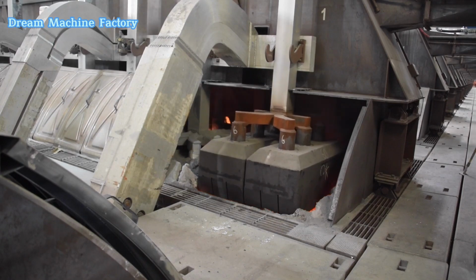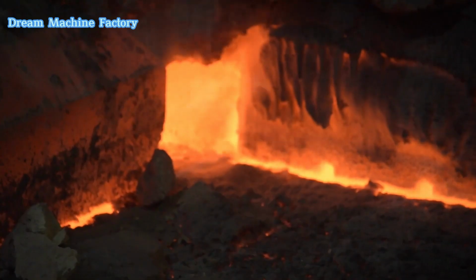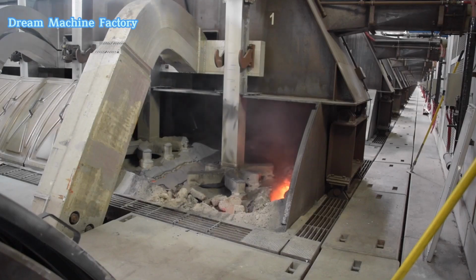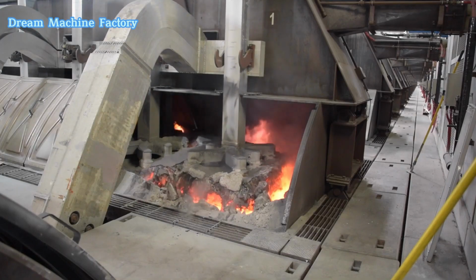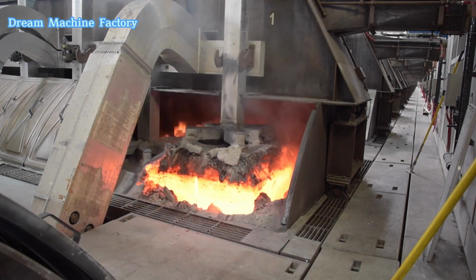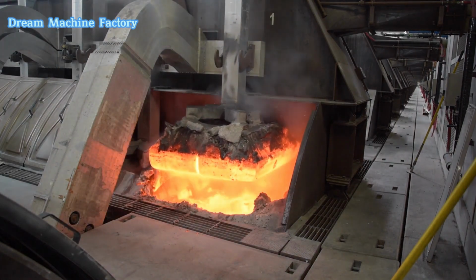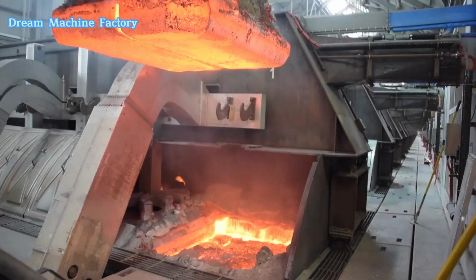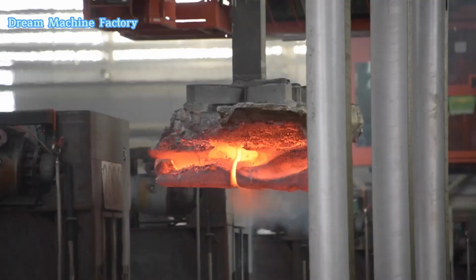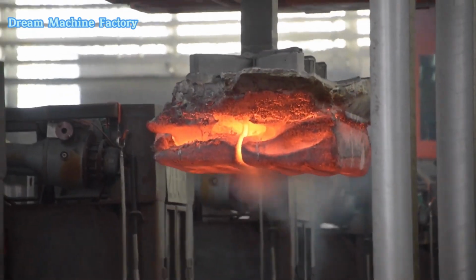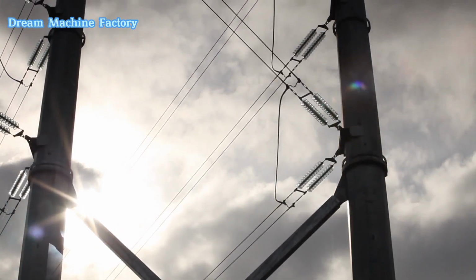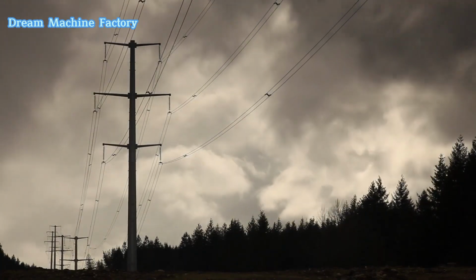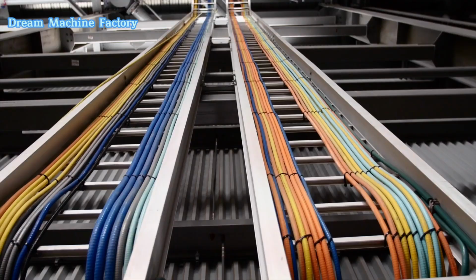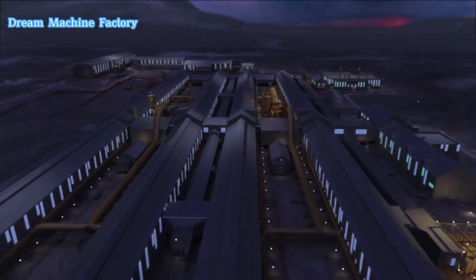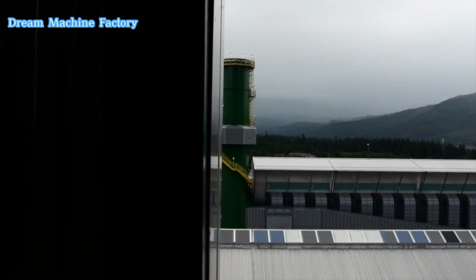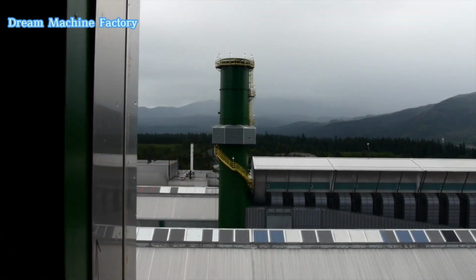These carbon anodes gradually burn out over approximately 20 days due to the intense heat and chemical reactions involved in the reduction process. When depleted, the anodes are efficiently replaced without interrupting the smelting operation, maintaining process stability and productivity. The spent anode material is fully recycled on-site, contributing to sustainability. Enhanced by state-of-the-art gas and fume treatment centers, the facility achieves a 50% reduction in overall emissions, significantly improving its environmental footprint and reinforcing its commitment to clean, efficient aluminium production.